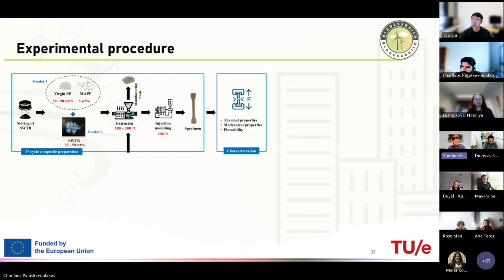So at first, we extruded the material by combining both virgin polypropylene and the shredded wind turbine blade waste. In the extrusion process, as you can see, we used a temperature range of around 180 to 200 degrees Celsius. After which we also made use of injection molding to produce all sorts of specimens with different compositions. And once we produced the specimens, we also wanted to characterize them for different properties. So we analyzed thermal properties, mechanical and other characteristics for these specimens.